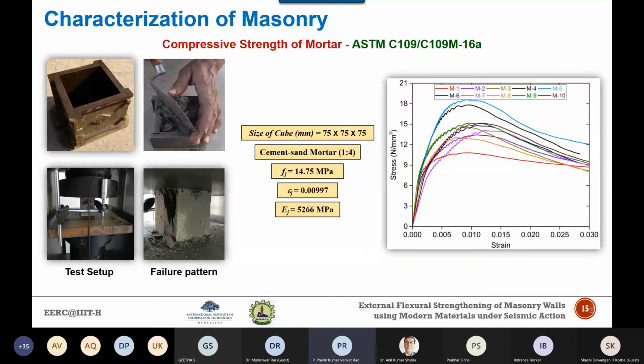So the most important guideline is, if you want to construct any building, then the cement mortar used should be either 1:4 or slightly higher than that, but not less than 1:6. And therefore, in this case study, we have chosen 1:4 cement mortar. We have prepared 75 by 75 by 75 mm mortar cubes, and after 28 days of curing, based on ASTM C109 guidelines, we tested them under compression. The mortar strength we got here is 14.75 MPa, and the modulus of elasticity is 5266.